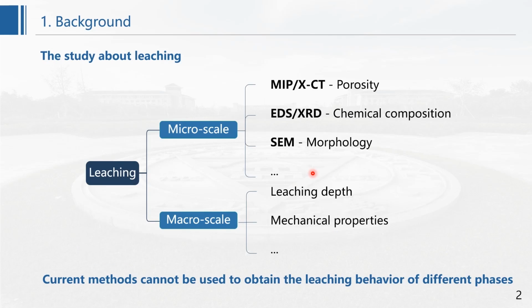To understand the effect of leaching on cementitious materials, researchers have done a lot of work using various testing methods. Here are some commonly used methods. From the micro level, people use MIP or XCT to obtain the porosity of leached materials, and use EDS and XRD to see the chemical composition change of leached materials. From the macro scale, people usually try to obtain the leaching depths and the mechanical properties of leached material. However, current methods cannot be used to obtain the leaching behavior of different phases.